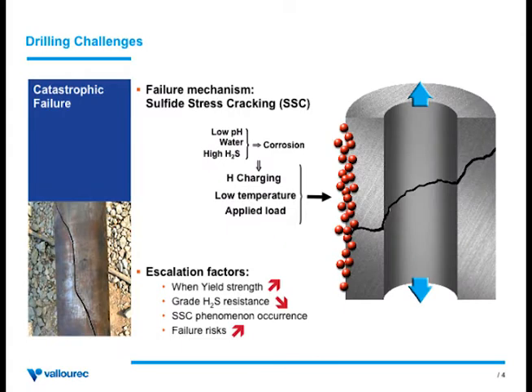And it's very catastrophic because you would basically have the material behaving as a brittle material, such as glass if you throw a stone on a window. Without entering into too many details, this is how the mechanism can occur. You need to have the combination of unfavorable factors to have this kind of failure occurring. First of all, you need acid conditions, the presence of water, and of course H2S in a significant amount, so you can have this corrosion mechanism starting.